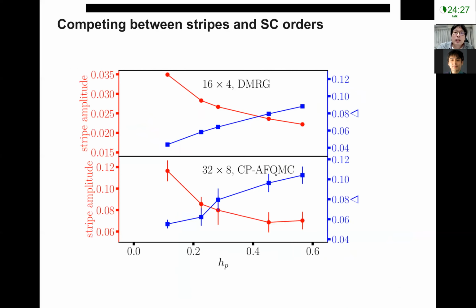We also show that the superconductivity is competing with the stripe state. Here the blue curve is the superconducting order, and the red curve is the stripe amplitude, or how strong the stripe order is. You see that whenever the superconductivity becomes stronger, the stripe order becomes weaker - so they're most likely competing with each other.